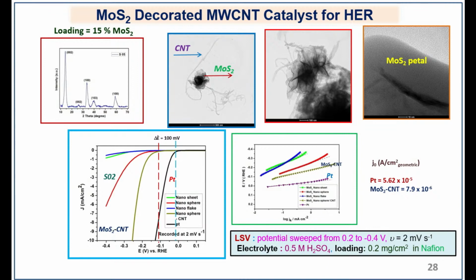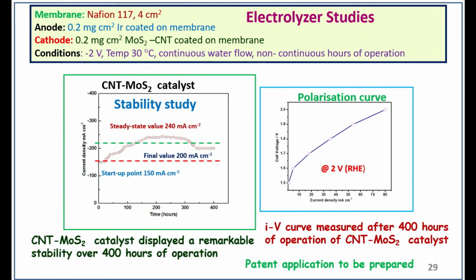So we went for further analysis, where we did a single cell test using Nafion 117, 4 centimeter square, with 0.2 milligram iridium for the anode and 0.2 milligrams MoS2 CNT as the cathode. Now we can see that the current density improved quite a lot. Earlier it was 65 milliampere, right? Now I decorated MoS2 only over the CNT top, and I am able to reach around 240 milliampere at steady state, and we operated the cell for 400 hours continuously. It's a very important long-term operating condition, because we need it for long-term hydrogen generation.